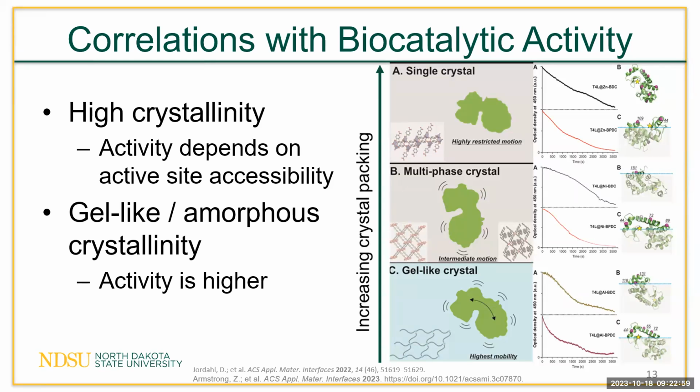You might notice that on the top right, zinc BDC actually doesn't show any orientation. This was because there was no spin label that was more likely to be mobile versus immobile when you compared the eight spin labels all together. So we concluded that there was completely random orientation for all proteins, and almost no preferred orientation. It should be noted that these orientations are educated guesses on the most likely orientation based off of which spin labels on the protein were shown to have the highest mobility.